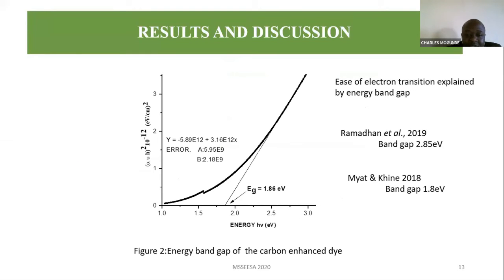The band gap was determined by Tauc correlation, and it lies at just 1.86 electron volts, and it is within other research which was done by Ramadan and Ahmad in 2018 and 2019. Next slide, 14.